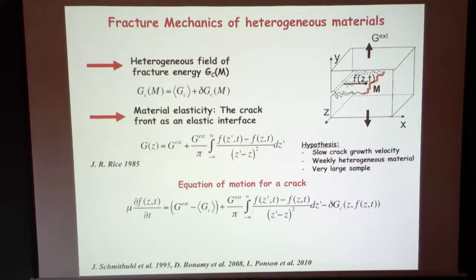So what does it do? The crack will start to accelerate, and then this mu stops being trivial and starts to become actually a singular function of the crack velocity. As long as you're putting in energy at the same rate it's being dissipated, and you're always making sure that everything is kosher at the crack front, then it's relatively simple. I'll show you examples maybe tomorrow when the crack starts to move like a bat out of hell, or starts to approach its asymptotic velocity, which is the sound speed, and then things become funny. So if you pre-stress it or something like that. Yeah, an example.